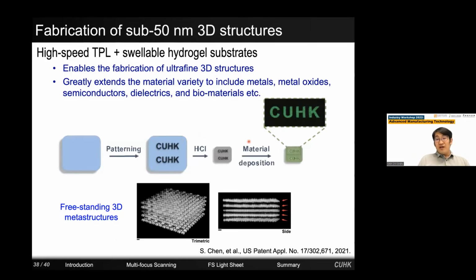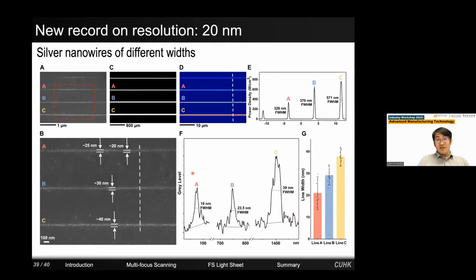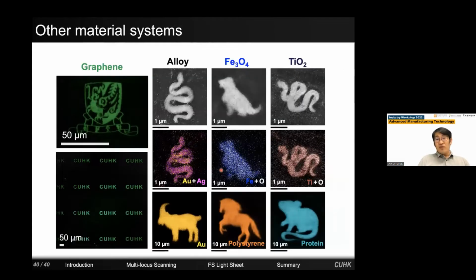And after that, we follow by a material deposition process. And lastly, we can shrink the hydrogel by putting it into the hydrochloric acid. As a result, we can create all these freestanding three-dimensional metastructures of 20 nanometer resolution. And you can see the resolution test to be less than 50 nanometers. We also try with different materials. The materials now include metals, metal alloys, metal oxides, semiconductors, or even biomaterials.